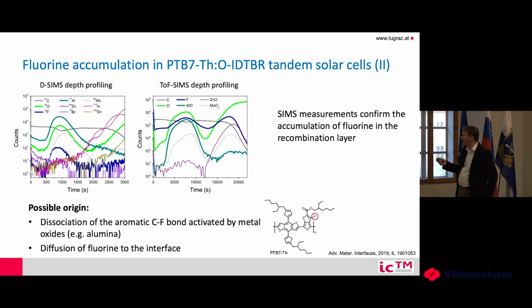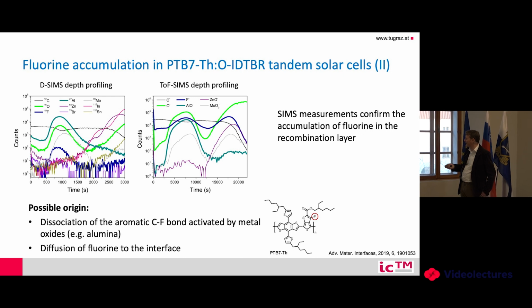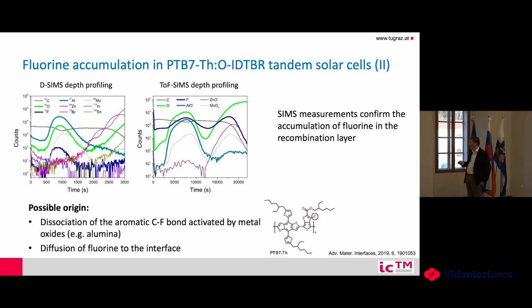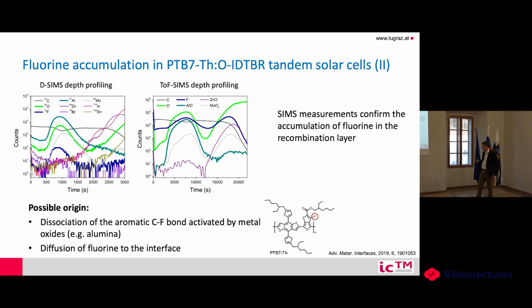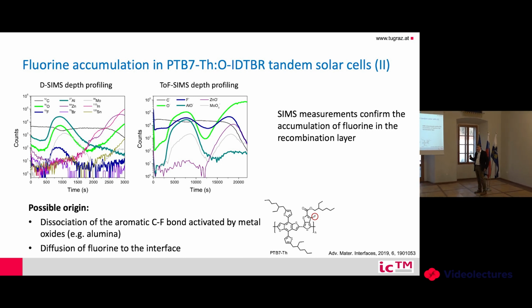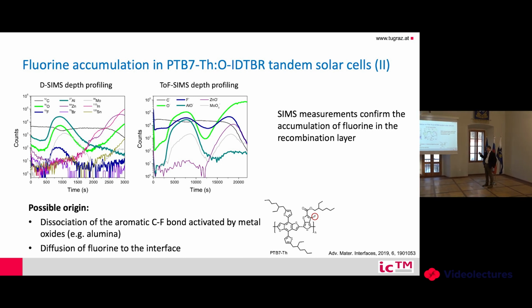Yeah, we also used TOF-SIMS, a different method. We also proved that we find the fluorine, because you also have to check that you don't have any sample artifacts. So with two independent methods, we really proved that the fluorine and the aluminium are reacting with each other.